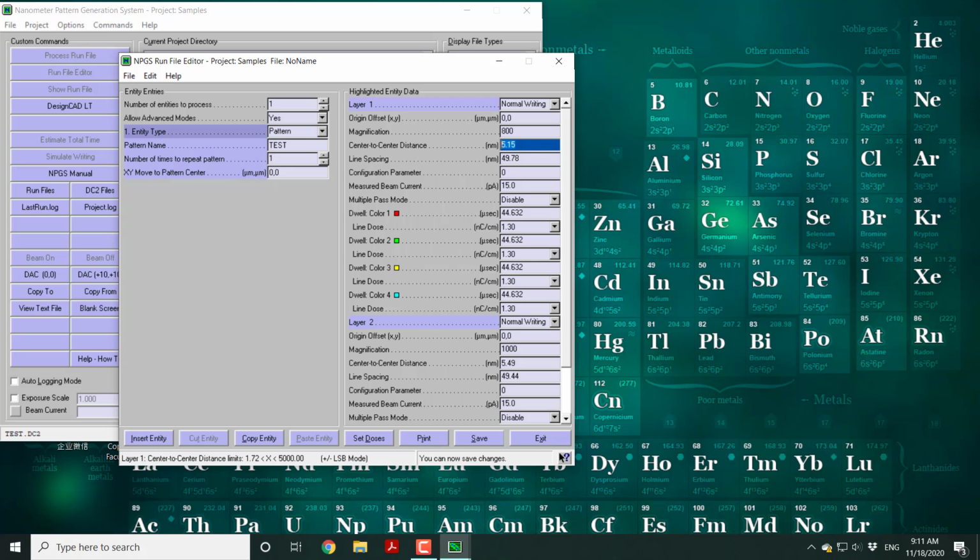The recommendation is I usually do around 10 nanometers, and the line spacing, depending on your requirement, could also be 10, let's say. In that case, it's going to create very fine patterns. If your pattern is big, like 50 nanometers and 50 nanometers would be sufficient.